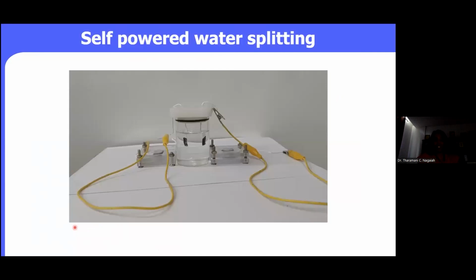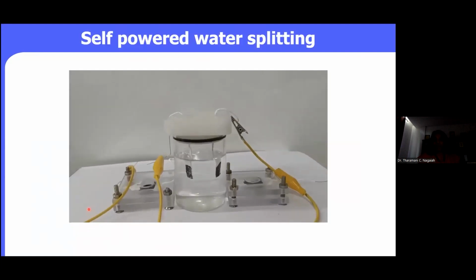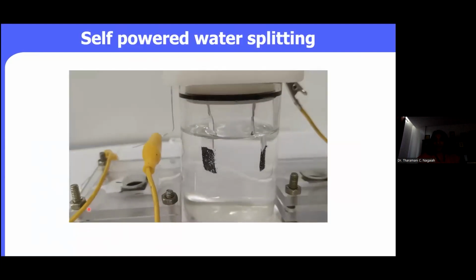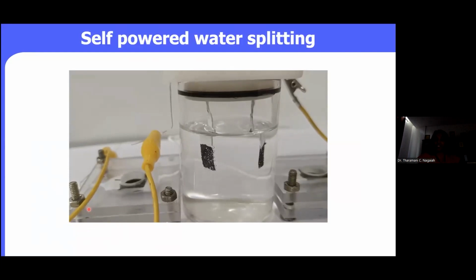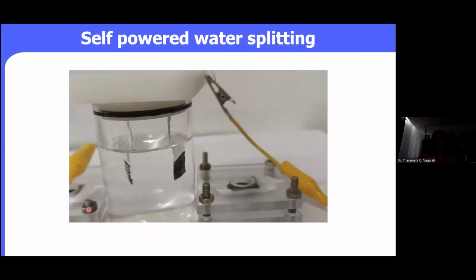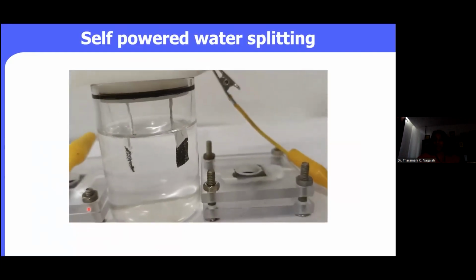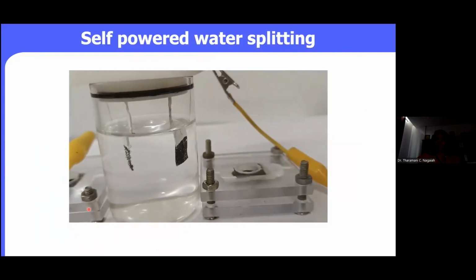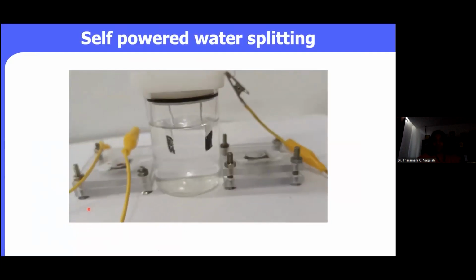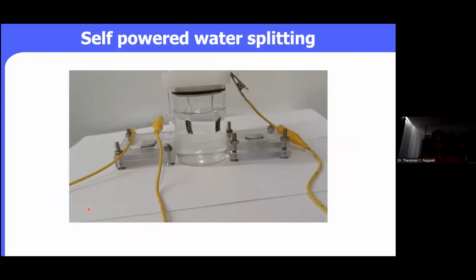So this is the demonstration of the water splitting. You can see that we are not using any external power sources, and we have connected two zinc air batteries in series, and we could see the bubbles on the electrode surface. So this is due to the production of the hydrogen, and this is what we are demonstrating, the self-powered water splitting here.